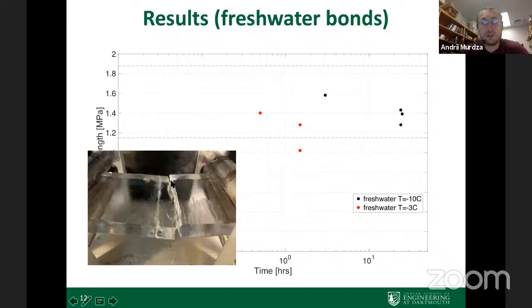the failure occurred outside the bond. On this image, you can see that the freeze bond was on the left, although the failure occurred on the right. So it indicates that in all cases, the bond was probably stronger than the parent material.